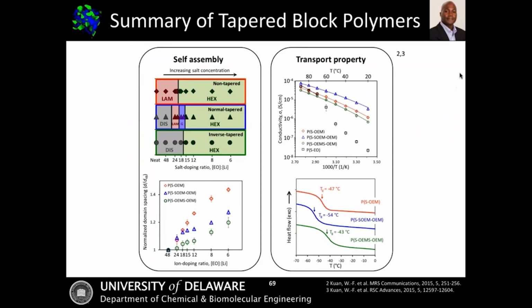Now, why is that? And so the first part is just a summary of what you already saw before, both in terms of not only the self-assembly, but also one measure of the interactions between the systems. On the right-hand side, basically what you're looking at is the conductivity here, and now the explanation for it. So as Joe mentioned in the previous talk, glass transition temperature is very key to the transport and conductivity in these particular systems. So this is just one example here, where now you can see in that blue curve, which was again that highest conducting sample, we actually were able to measure the lowest glass transition temperature, whereas the sample in green that had the lowest conductivity of the three tapered materials, it actually has the highest Tg.